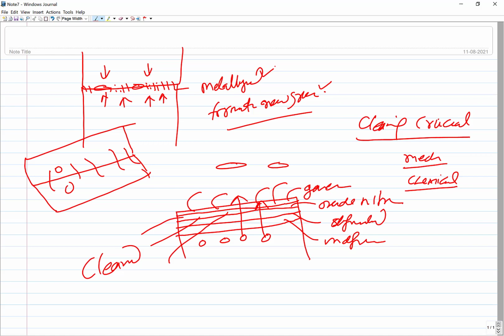whether it is the macro deformation or micro, for diffusion to take place, primarily we need the interfacial surface layer deformation. Bulk deformation may not be helping you in any way. I'll tell you an example. Like say this is the component. So if the deformation near the interface of a few micrometers is taking place, like 5 or 10 micrometers, which corresponds to the peaks and valleys present at the surface, it's fine.